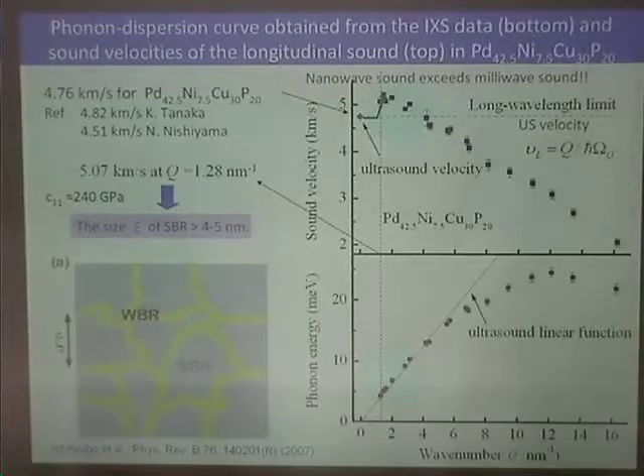So I guess I'm not understanding exactly what the main point of this is. In some Q range, you're interacting with some local region in the structure, and within that region, it seems to be stiffer than the crystals. So you're getting a higher sound velocity and hence higher elastic constants. But then at another Q range, you're getting a lower sound velocity. So this is usually a dispersion. Dispersion, yes.